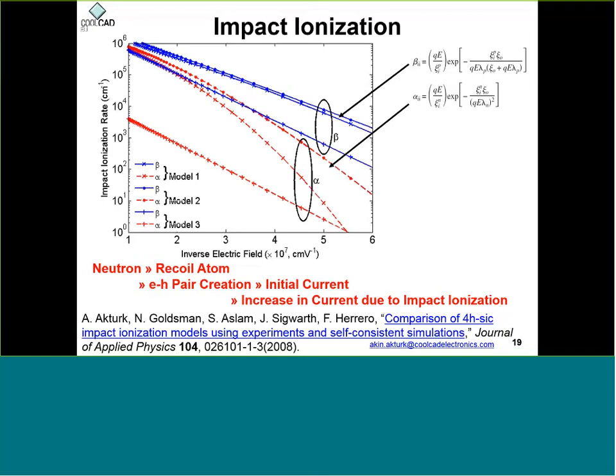How much Joule heating you get is related, in some part, to impact ionization, because the original neutron doesn't have enough energy to create enough electron hole pairs to give rise to the failure rates we observe. So the gain comes from impact ionization. In the blocking state, normally you don't have impact ionization, but once you increase the current by creating electron hole pairs, you have impact ionization happening at a lower voltage, and that can sustain a current for a long period of time, until the device fails or literally melts down along the track of the primary neutron.